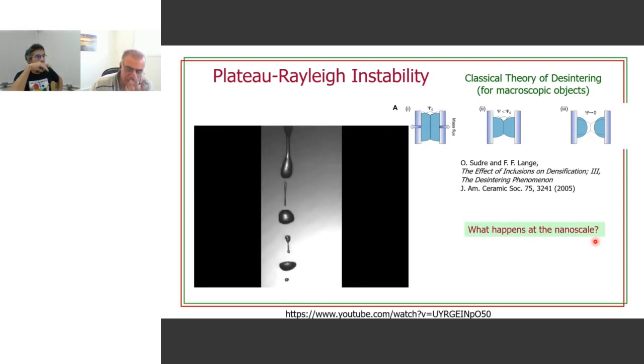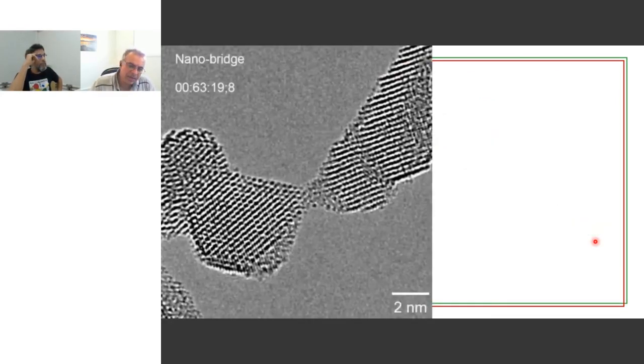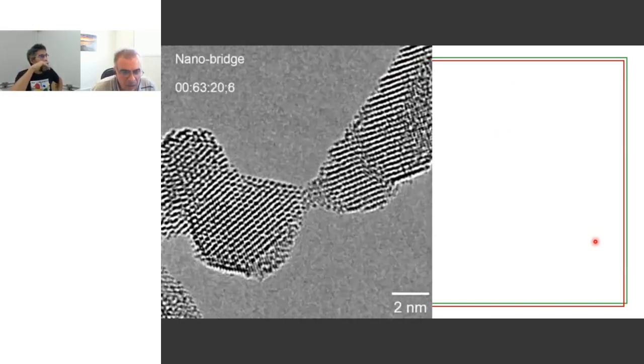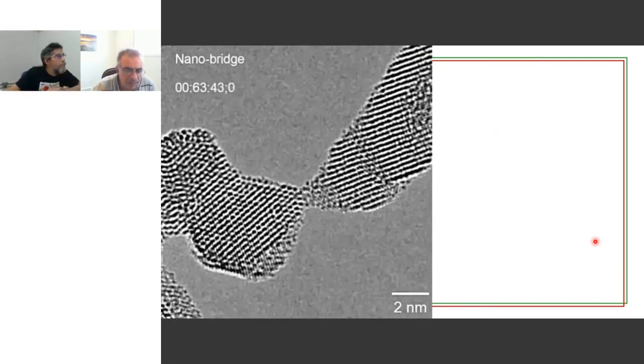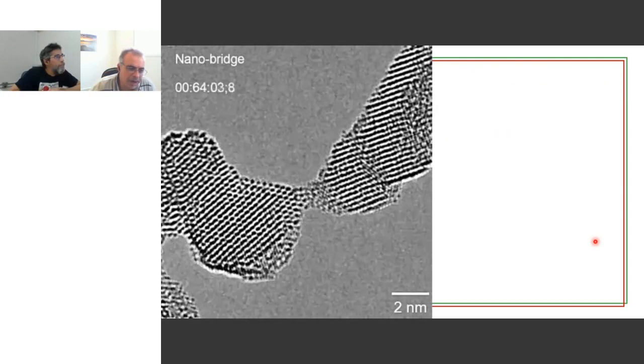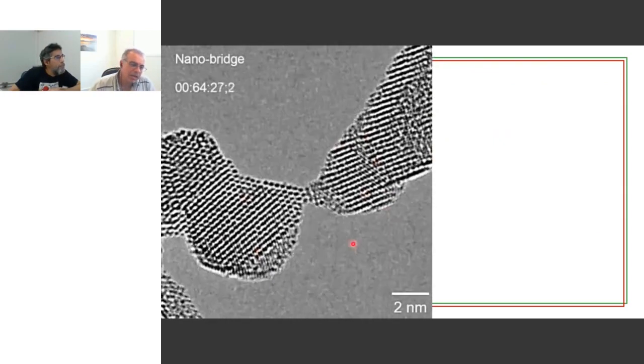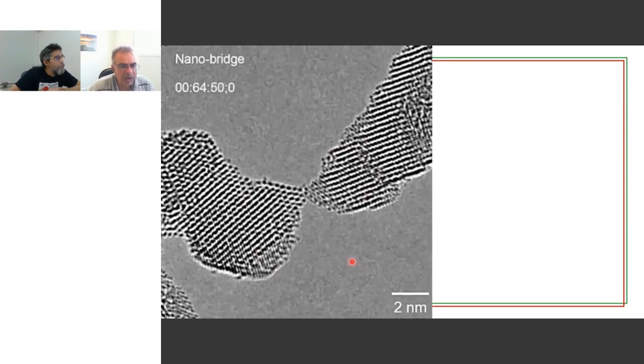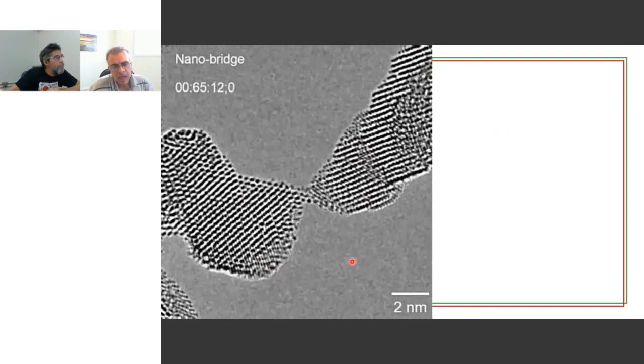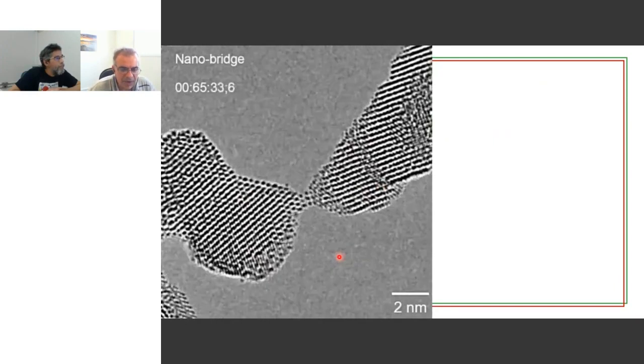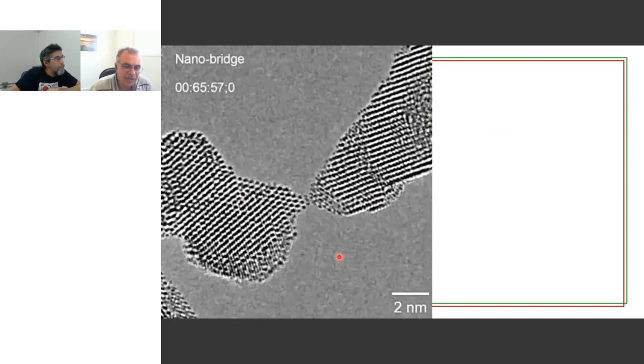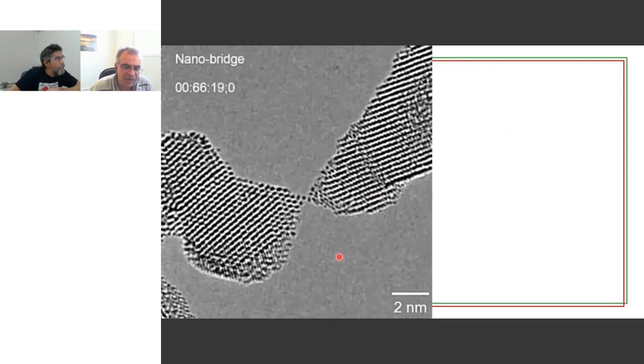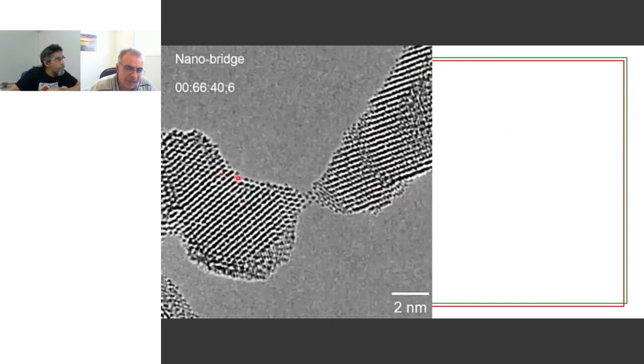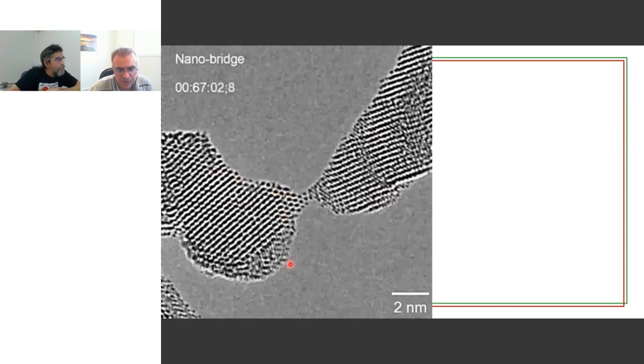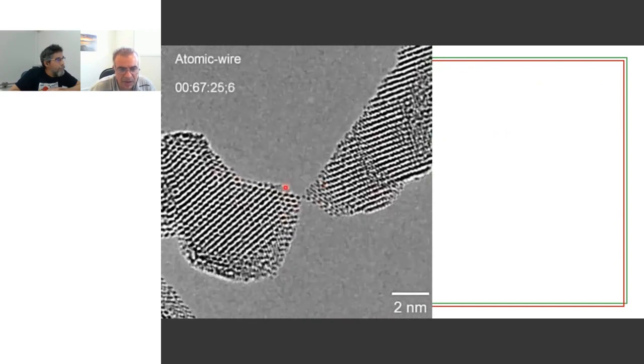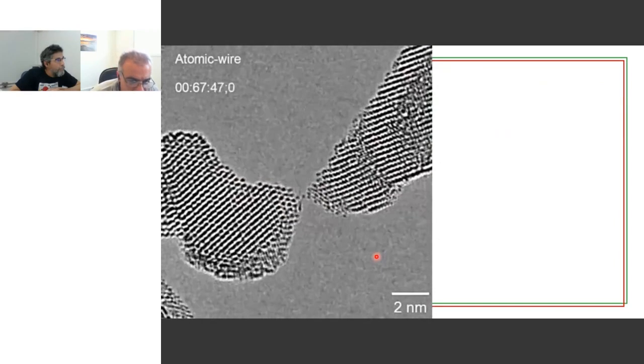So the basic question is, as usual, what happens at the nanoscale? So let's see what happens at the nanoscale. This is, again with higher resolution, our movie of breaking these two zirconium nanoparticles. The black dots that you see here are zirconium atoms. You don't have the resolution to see the oxygen atoms. And here you can see something that is very intriguing and important. This is very different from the classical description. First of all, you don't see any instability. You see that the sintering process goes through until the very end, until you form a monatomic zirconium oxide wire, as you can see right now.